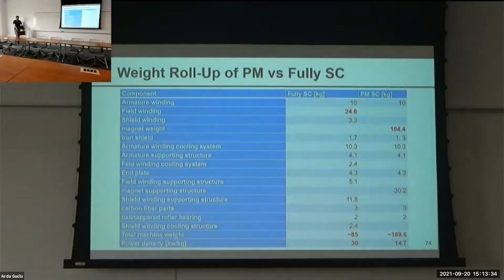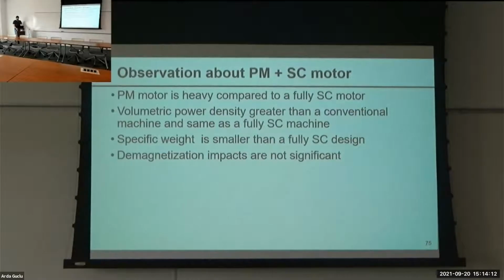And here's a more detailed comparison of the partially superconducting motor design versus the fully superconducting design. As you can see, the magnet weight really contributes a lot to the total weight of the motor, and the power density for fully superconducting is about twice as much as for the partially superconducting. But it should still be noted that the power density of the partially superconducting machine is pretty good compared to conventional machines. But the fully superconducting machine is clearly better. Again, the permanent magnet motor is heavier compared to the fully superconducting motor.